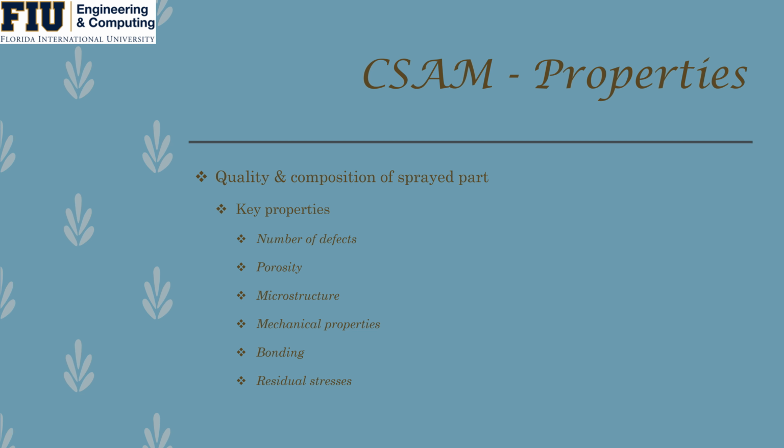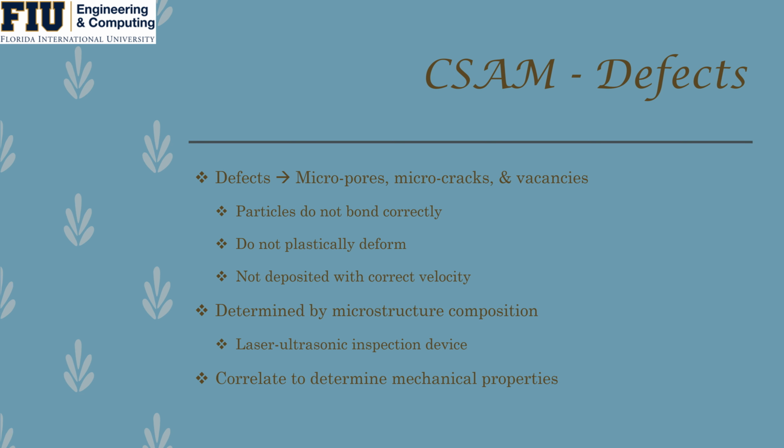The quality and composition of a sprayed part has a number of key properties associated with it, such as the number of defects, the microstructure composition, as well as the overall mechanical properties of this part. These defects come in the form of micropores, microcracks, and vacancies due to particles not bonding correctly, not plastically deforming enough, and not being deposited with the correct velocity. This can all be determined by its microstructure composition, and researchers are also using laser ultrasonic inspection devices to see these defects. This all correlates with determining the mechanical properties.